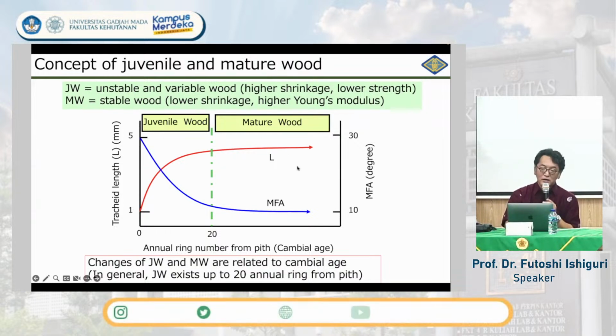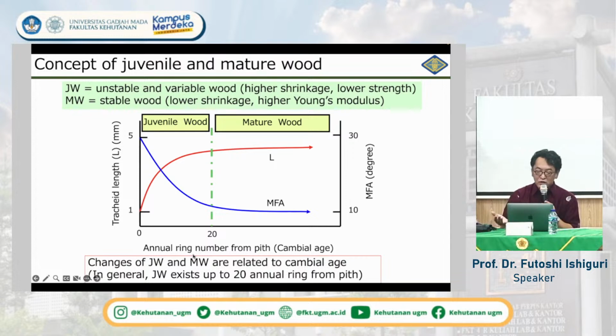Anyway, we sometimes determine the juvenile wood and the mature wood by using the length of the cell. In this case, the tracheid length and also the microfibril angle, the radial variation of these factors. The microfibril angles decrease and become stable, and the tracheid lengths increase and then become stable. The starting point of becoming stable, as I told you before, is around the 20th annual ring from the pith. We call it the cambial age, 20 years cambial age. So in general, here we call it juvenile wood, and here we call it mature wood.